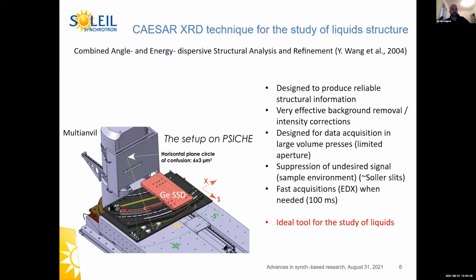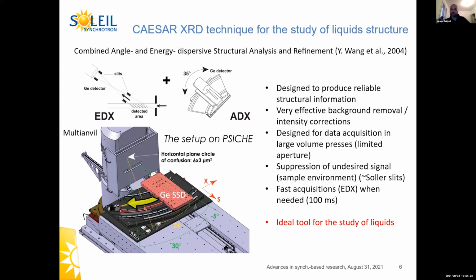So the first technique I would like to present is the CAESAR X-ray diffraction technique. CAESAR stands for Combined Angle and Energy Dispersive Structural Analysis and Refinement. It has been introduced by Yanbin Wang and collaborators in 2004. So basically, it's combining energy dispersive and angular dispersive X-ray diffraction. The detector is mounted on this rotation axis, and the slits in front of the detector are always aligned with the sample, whatever the angle, at all angles.